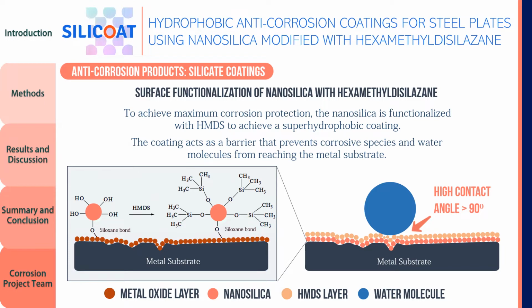In addition, in order to develop an effective coating with nanosilica against corrosion, the coating has to be hydrophobic. In this study, hexamethyldisilazane was used for surface functionalization of nanosilica.